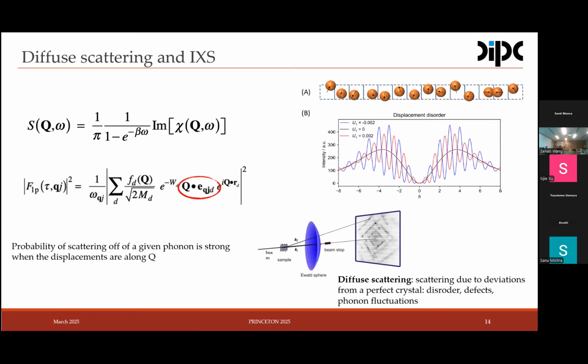The key point in this inelastic X-ray scattering experiment is that we will see a phonon. A photon will scatter off a phonon if the polarization eigenvector of this phonon is parallel to the momentum transfer in the crystal. With that selection rule, we can move from transversal to longitudinal modes, and we can selectively measure in different positions of the Brillouin zone, and selectively probe different phonons of the crystal.